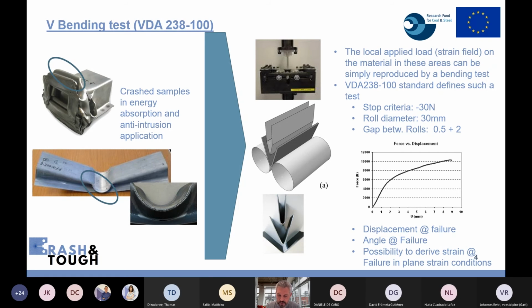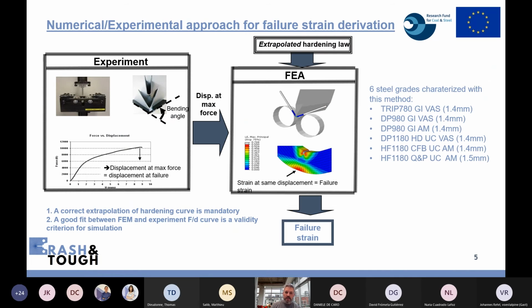And considering this test, we can measure the displacement at failure of the punch, which can give an important result in terms of classification of the product. We can also measure the angle, which is generally considered by the car maker to evaluate the product. So how do we extract the fracture strain thanks to this result?